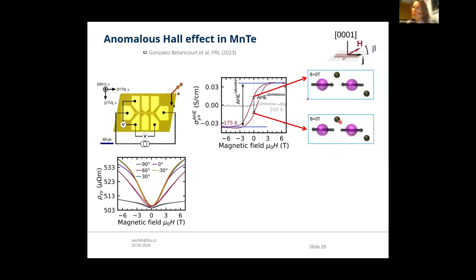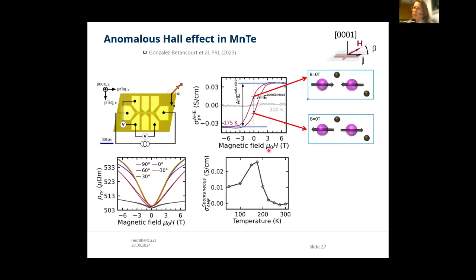So here I schematically highlight again that although they have no net magnetic moment, they don't need any net magnetic moment. The presence of this non-magnetic environment is enough to allow for the difference in the anomalous Hall effect. And the spontaneous signal indeed disappears at higher temperatures. The critical temperature is around room temperature. Here it's closing a bit below the critical temperature, but simply it behaves as one would expect.